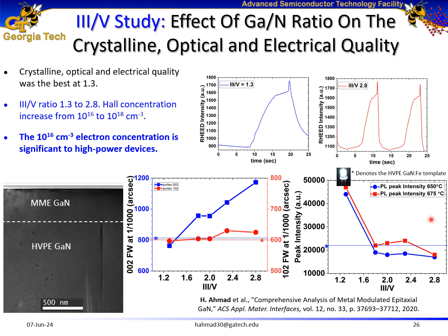Then I fixed the excess gallium dose at 12 monolayers open time, and I studied the effect of 3:5 ratio in the range of 1.3 to 2.8. And from electrical, structural and optical measurements, we found that the 3:5 ratio of 1.3 gives us the best results. And also in terms of electron concentration, it gave electron concentration of 10 to the power of 16 per centimeter cube, a significant result for n-type doping and also for high power devices.